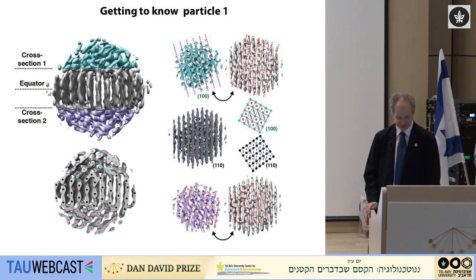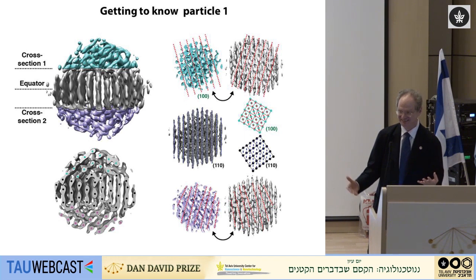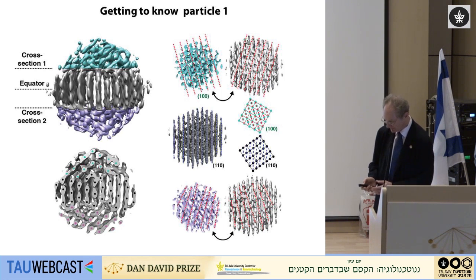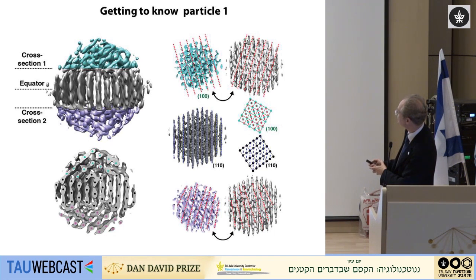So this is an example. To my knowledge, this is actually the first example where the position of every atom inside a sample, where every crystal is not the same, which is a typical human-made construct of this size, we can observe the electron density inside it. You saw earlier that these particular crystals like to fuse, and so these are some of the fusion events that have taken place. And if we look, for example, there's a grain boundary where some crystals fused, and we can go in now and say, here are all the atoms, and you can see this grain boundary is not flat.